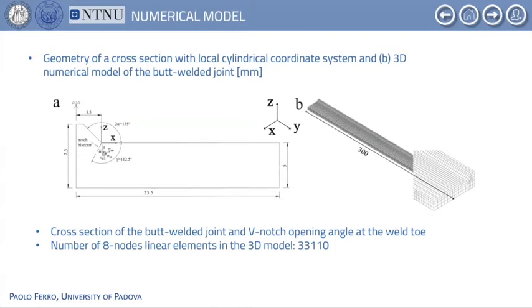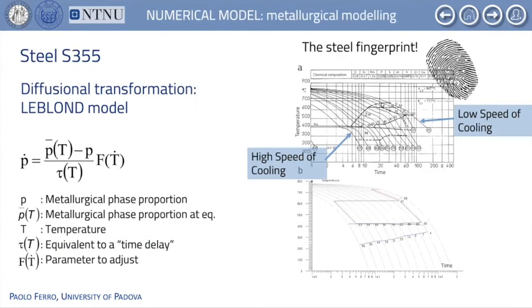33,110 8-node brick elements were used to build the mesh, the smallest ones in the vicinity of the weld toe having a size of 1 millimeter. It is shown that the weld toe profile is assumed to be a sharp V-notch with an opening angle of 135 degrees and a null tip radius, which is the worst case condition.